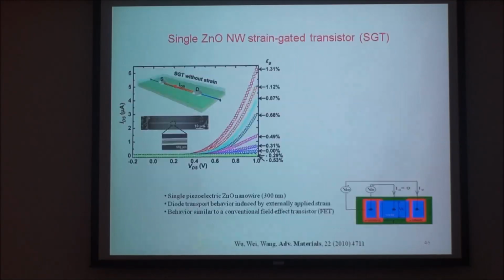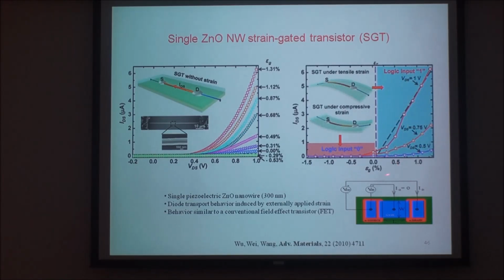It truly works. For the first one, let's make a single device on a polymer substrate. This is the device itself, and you apply the strain, because on a polymer substrate you can simply apply the strain. Then you measure the transport. This is the transport property here. If you fix the source-drain voltage and replot this, you get this. This is the strain applied. Under tensile strain, it is on.